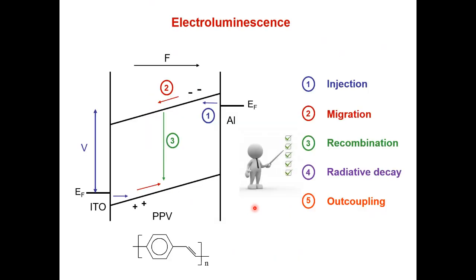Okay, what is the principle? We will go quickly, but you will see that it's not easy to make light from organic material. So basically, you have to apply, these are the two electrodes here, aluminum on one side, the ITO on the other side, and they have different Fermi energies. The Fermi energy is the border between the valence band below and the conduction band above. And in between, you have the polymer chains. There are many, many of them. And when you apply a bias between the two electrodes, what you are doing is generating an electric field, and this electric field will make, this is back to physics, a gradient of the energy potential. This should be seen as the bottom of the conduction band of the polymers changing across the material.